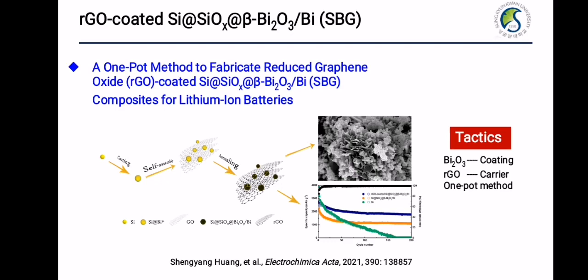Finally, after the annealing treatment, the bismuth ion intermediate shell would transform to a bismuth oxide shell and simultaneously oxidize the surface silicon to a silicon oxide thin shell, while graphene oxide would transform to reduced graphene oxide and then reduce the bismuth oxide back to bismuth.